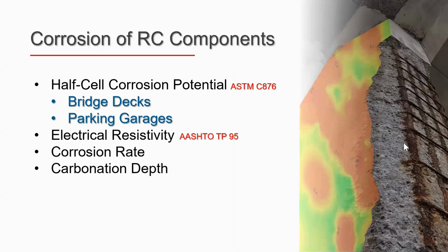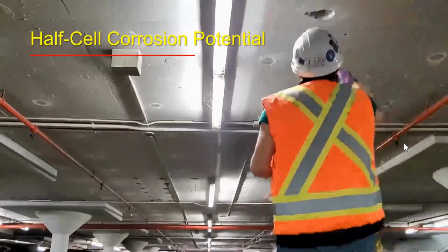Another group of tests that I would like to talk about is half-cell corrosion potential. Half-cell corrosion potential is a great tool to verify the corrosion activity in concrete structures. This is widely used for pre-bridge deck condition survey, but it is also very useful in parking garages, especially if they are exposed to de-icing agents such as salt. Half-cell corrosion potential maps, when developed and interpreted properly, can help engineers identify the likelihood of active corrosion in concrete elements. For your review, I have a short video on how the process is.